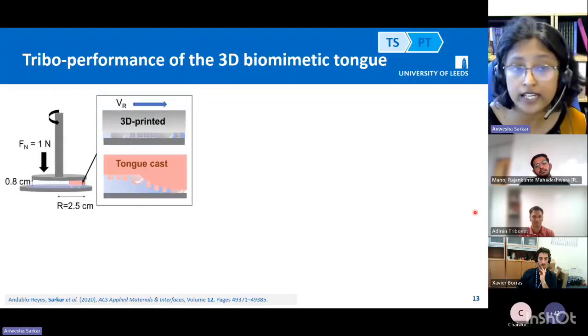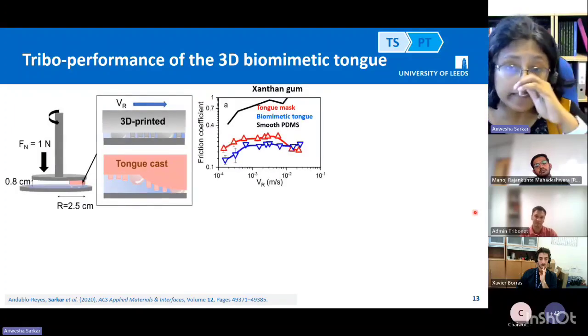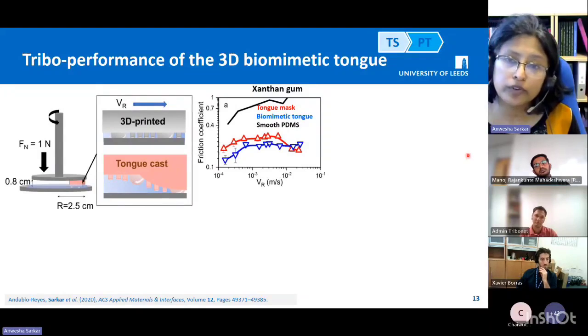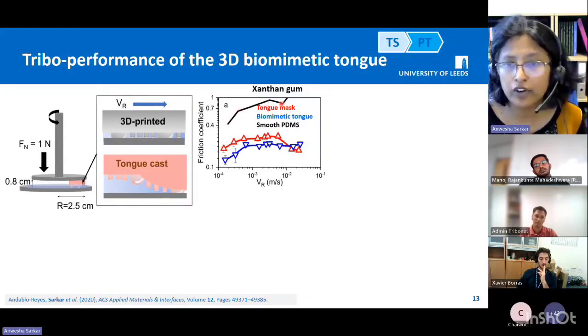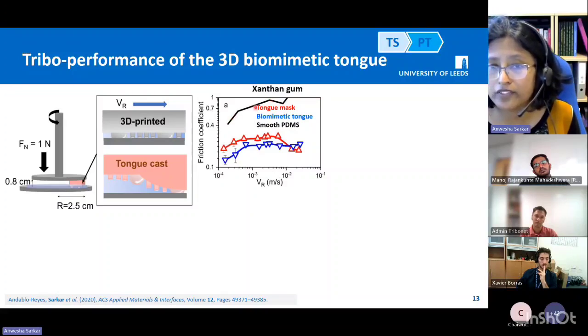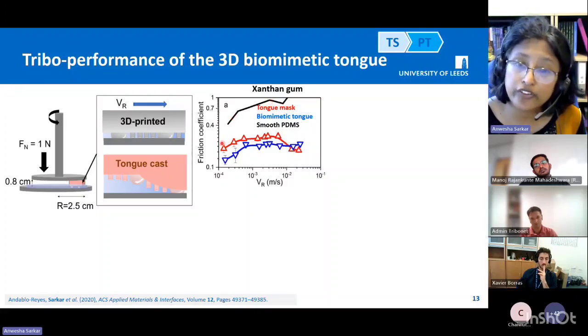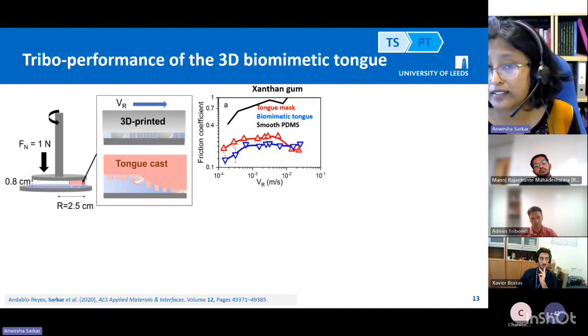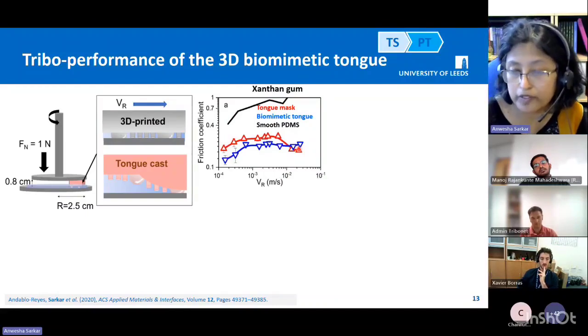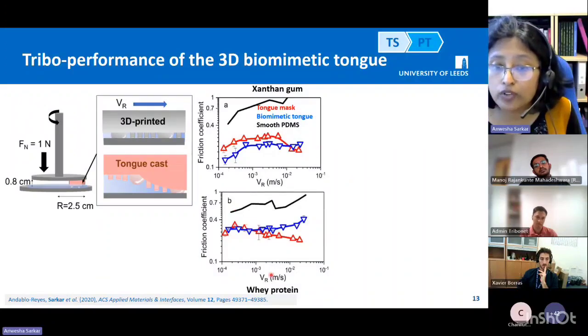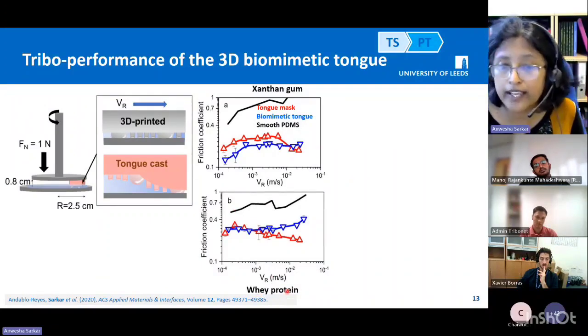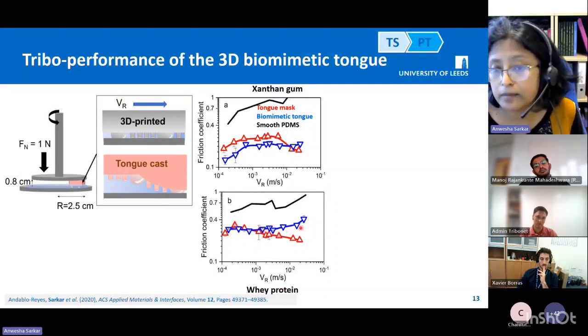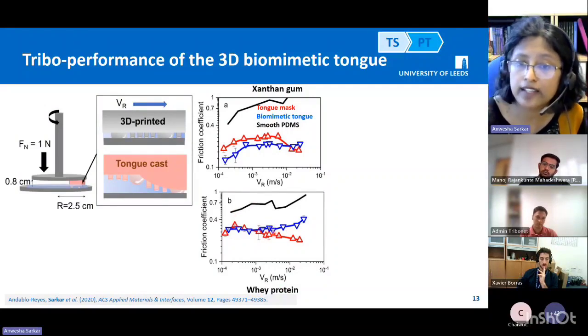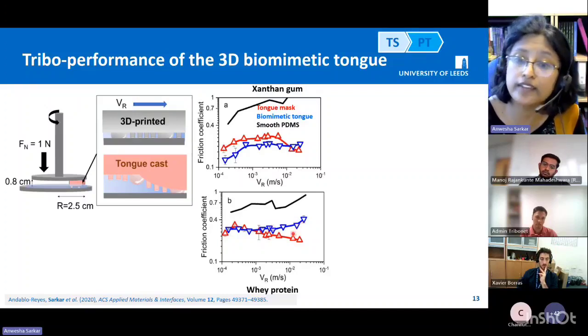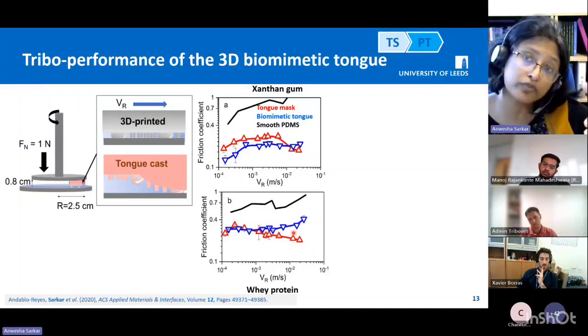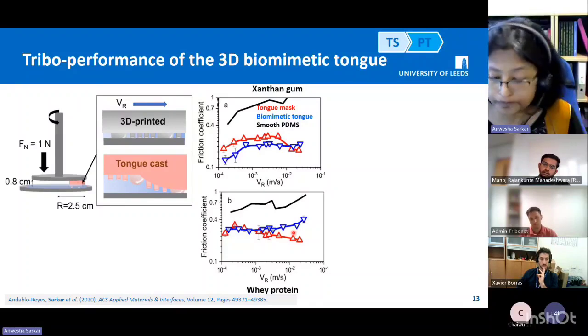So we did a tribology measurement, and we used xanthan gum, which is a polysaccharide. What you can see here is a friction curve of smooth PDMS with xanthan, this is a friction curve of our real tongue mask, and this is our biomimetic tongue surface. Which was very, very promising. We did the same thing also with whey protein, which is a protein. And here again, we can see the behavior of a real tongue mask, and here is the biomimetic. The difference is largely because of the shape difference and the elastohydrodynamic regime.